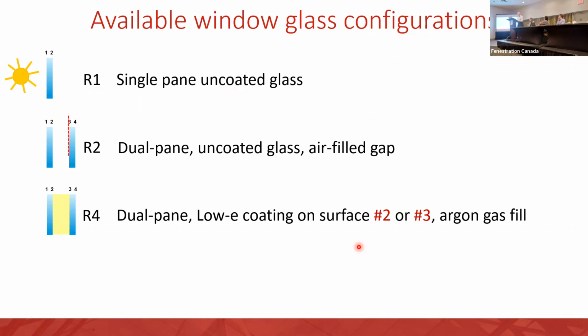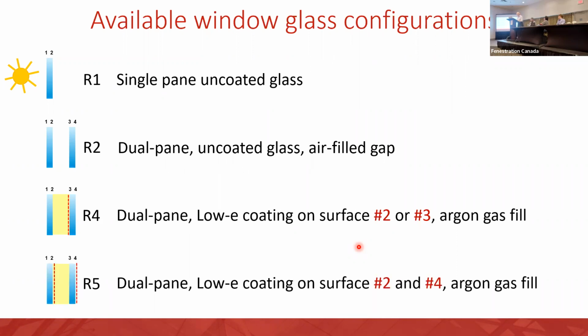Then we came with the idea of low-E coatings and argon fill, and whether your coating is on the 2 or on the 4 doesn't matter. Your R value is the same. It's still an R4. The U factor is the same, but you will get a little more heat captured with the coating on the number 3 surface than the number 2 surface. R5, well, we just add one more room-facing coating on this double pane unit. We now go up to R5. 2 low-E coatings.